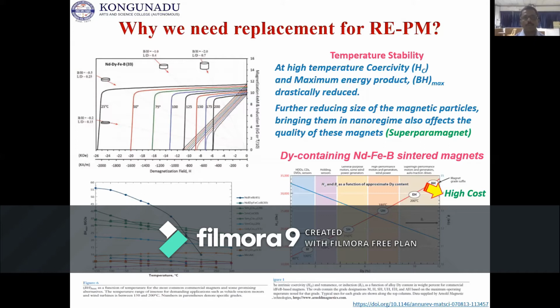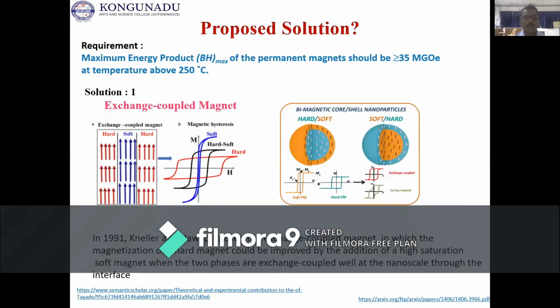So we want to solve all these issues: instability, cost, and operating efficiency. To overcome this sort of problem, our requirement for efficient electrical devices is a magnet with a maximum energy product greater than 35 mega Gauss Oersted, exhibited at 250 degrees Celsius and above, and we want to have 300 to 400 degrees Celsius. So the first solution proposed is the exchange coupled magnet, where the exchange coupled magnet will have two different phase magnets. One is a hard and one is a soft magnet.